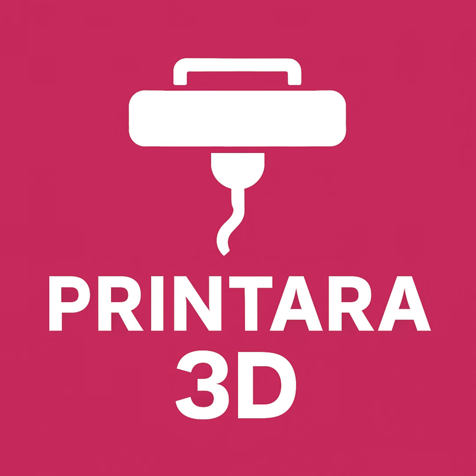What is actually happening at the molecular level when those vapors hit the plastic? Like, why does it smooth the part? The acetone vapors specifically target the styrene bonds on the very outer shell of the part. As the vapor touches the plastic, it breaks down those surface bonds.